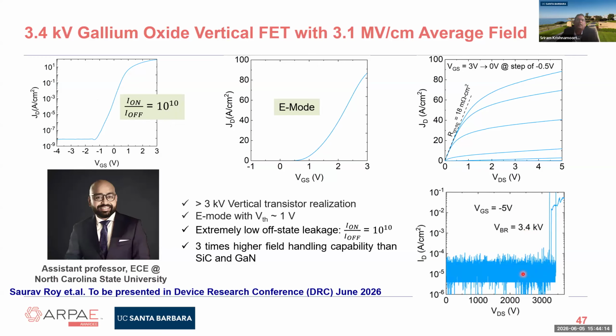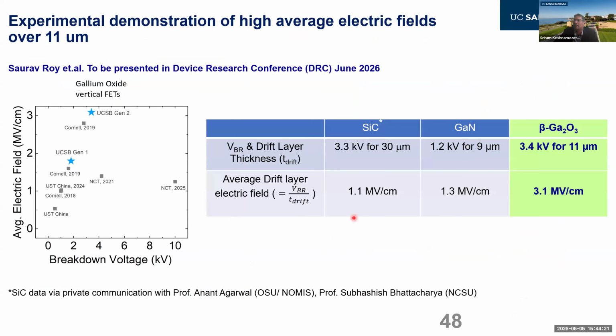So the most exciting part about this particular device and this generation of device is when we compare this to gallium nitride and silicon carbide. Although gallium nitride and silicon carbide can theoretically hold high electric fields, for a 3.3 kV device in silicon carbide, you actually need 30 microns of drift layer. And this translates to an average electric field handling capability of about 1 megavolt per centimeter. And that's the same for gallium nitride as well. These are gallium nitride FinFETs from MIT. Whereas in gallium oxide, we are able to block 3.4 kV with just 11 microns of drift layer, which translates to about 3 times higher electric field handling capability in this material compared to GaN and silicon carbide.